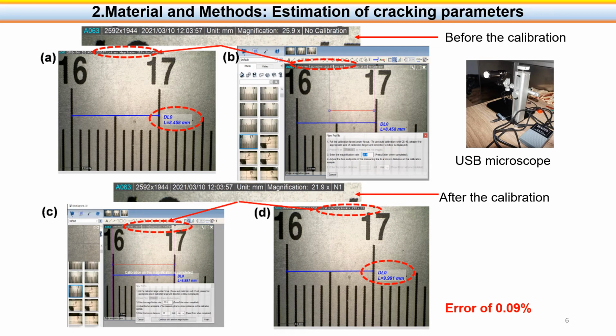This operation is done in 4 steps. The first one consists of taking an image with the microscope on which we have 2 reference points of known distance. In our case, we took an example with a ruler. When estimating the distance of this image, we notice that the distance reading is wrong because the real dimension of this image has not yet been calibrated. By calibrating this image with the magnification 25.9 and a known real distance of the image of 10 millimeters, we get a less erroneous reading of the measured distance. On the final image, we can see the measured distance is not the same as the known distance.